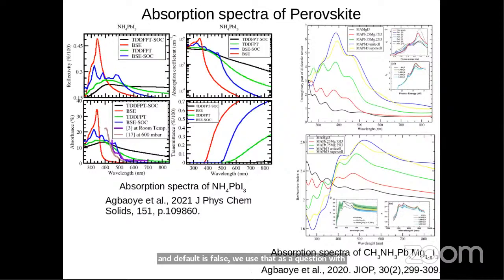Then we compare the result of the absorbance with 2 different experimental results. That is in work in 2021. And we realized that the Bethe-Salpeter method has similar results compared to the experimental value. But when the Bethe-Salpeter equation was used with spin-orbit coupling, it has much better results compared to ordinary BSE. So here we are able to establish that the Bethe-Salpeter equation works better than TDDFT, while using spin-orbit coupling on the Bethe-Salpeter equation, we're able to get a result that is much closer to the experimental value.